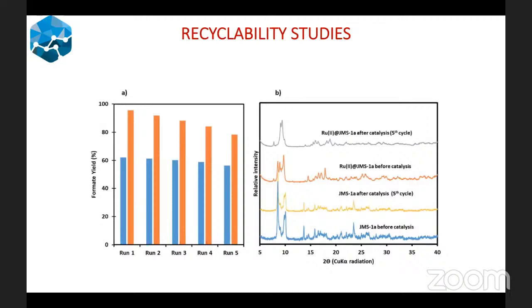This could be due to, when you are using your MOF, the ruthenium may depart, or the ruthenium may form nanoparticles which disintegrate or which agglomerate, and then of course that also causes a gradual decrease in catalytic activity. But of course it's not very bad, because the activity drops from close to 98% to about 80% after 5 runs, which I still believe is a very good catalyst. And of course, the yields that we got were close to 98%, which shows the need for inserting the ruthenium complex inside the MOF.